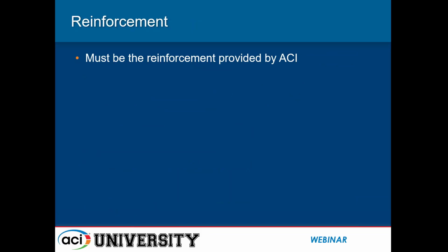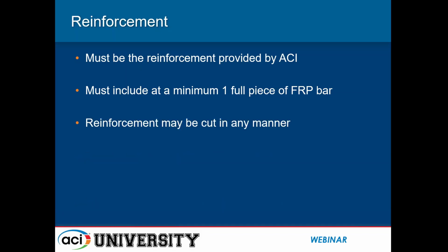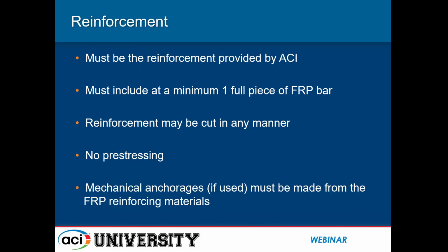For the reinforcement, as I mentioned previously, it must be the reinforcement provided to you in your kit by ACI. You must include in your member a minimum of 1 full piece of FRP bar. However, that bar may be cut into smaller segments if you choose to do so, but you must place all segments of at least 1 full piece of FRP bar into your member. So again, reinforcement may be cut in any manner. You are not allowed to pre-stress any of the reinforcement. And mechanical anchorages, if used, must be made from the FRP reinforcing materials. You are also allowed to select different manufacturers of the FRP bars. For example, you may combine one Marshall C bar with one Aslan bar if you choose to do so.